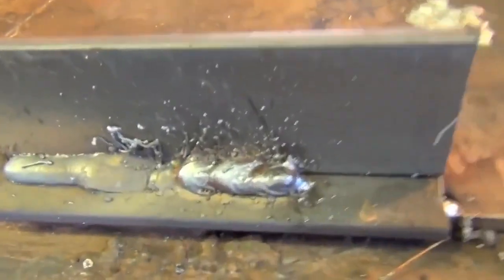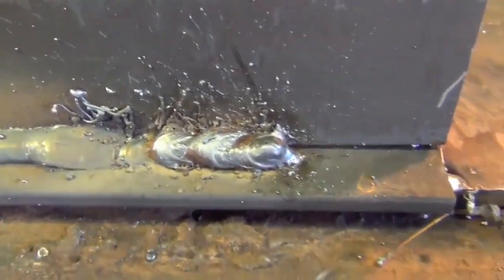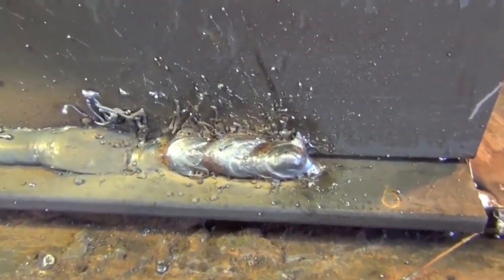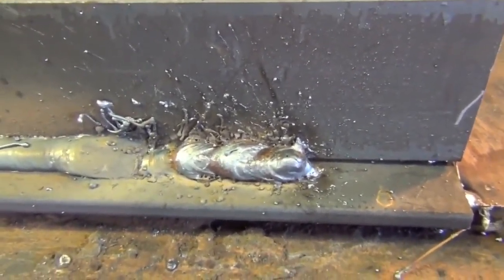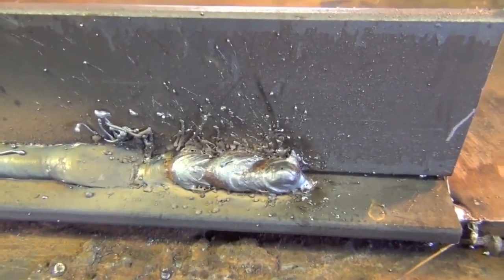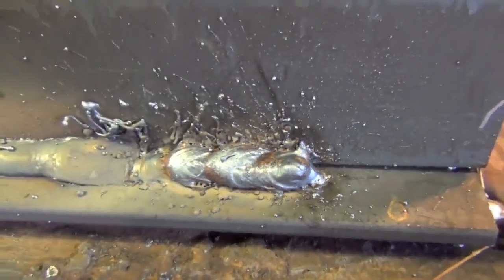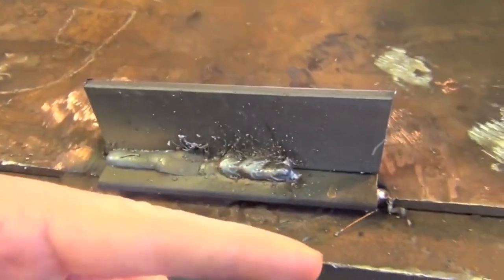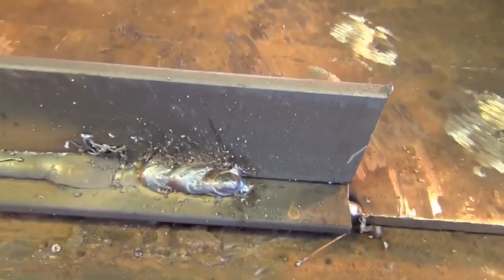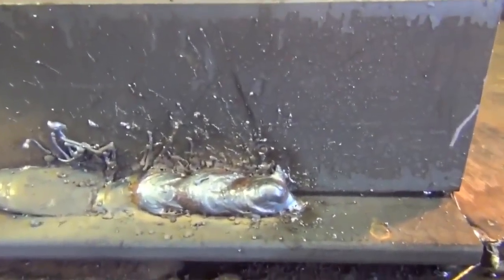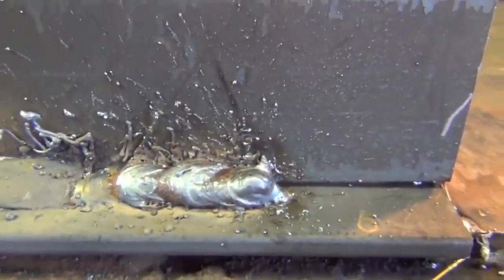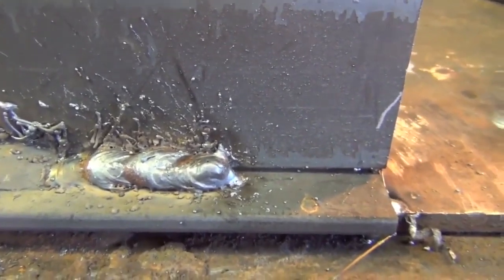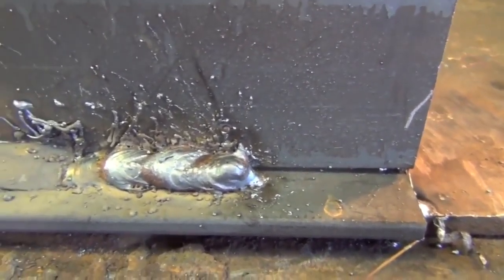Alright, let's have a look at this. As you can see, there's a lot of spatter, something that vaguely looks like a weld, and that's what it's going to be like if you're running way too much stick out. Now another thing, it looks like, especially down around here, we might be having some issues with gas coverage. Again, that's because we're holding the nozzle so far back that by the time the gas gets down to the weld, it's thinned out, it's dispersed a little bit, and it's not really doing its job. We got all those little broken off pieces of wire, and if you're running way too much stick out, well, now you know what that'll look like.